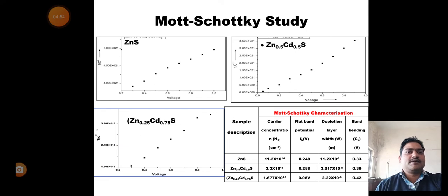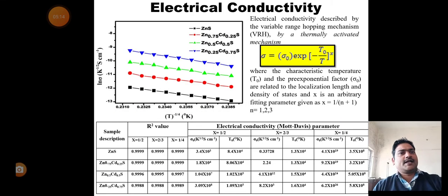The Mott-Schottky case study of zinc cadmium sulfide shows that the as-prepared sample has n-type conductivity and increasing band bending with increasing cadmium concentration of the zinc cadmium sulfide lattice. The electrical conductivity is best described by the variable range hopping mechanism, and the equation of the Davis model has been obtained for electrical conductance. I have also used fitting parameters in this sample, and the best fit R square value is x equal to 1/4. Thus it is concluded that our sample follows a thermally activated mechanism.